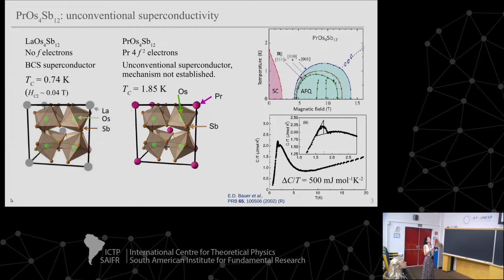This one is also a superconductor, but it's a simple S-wave BCS superconductor. It has a transition temperature of 740 millikelvin and a very low upper critical field. This one has, as I said, 1.85 Kelvin and a 2.2 Tesla Hc2. So it's much more robust superconductivity, and this has to be because of the F electrons.